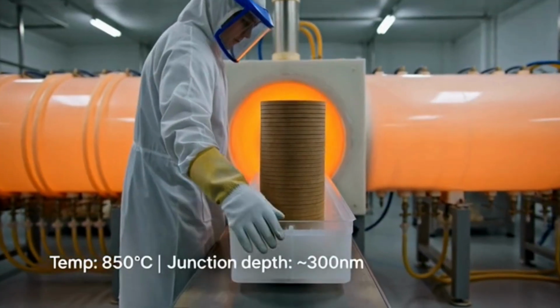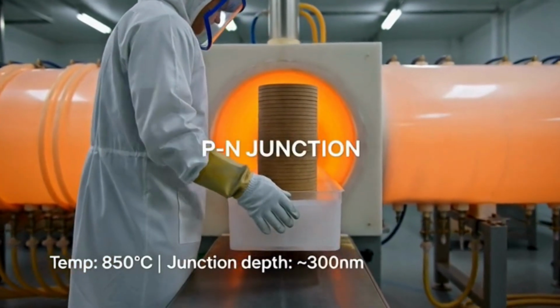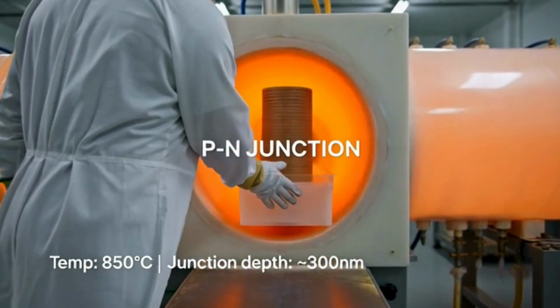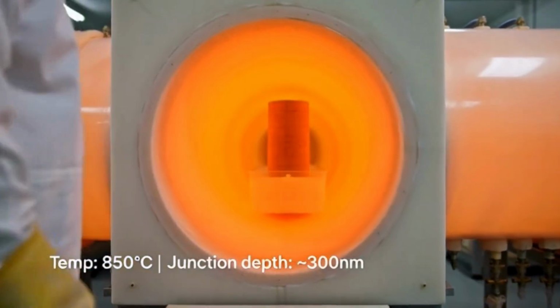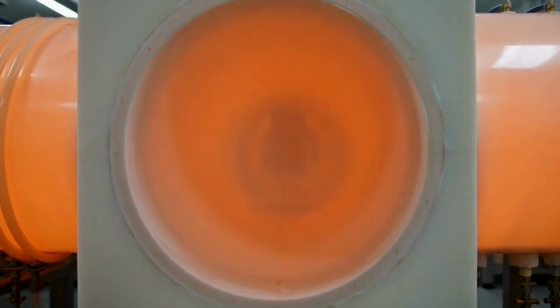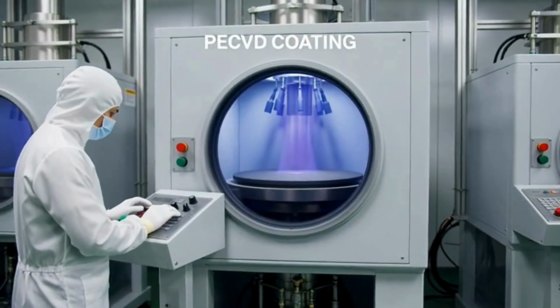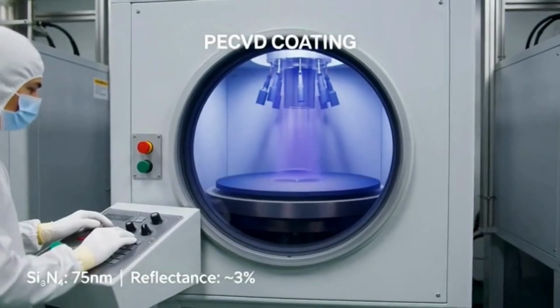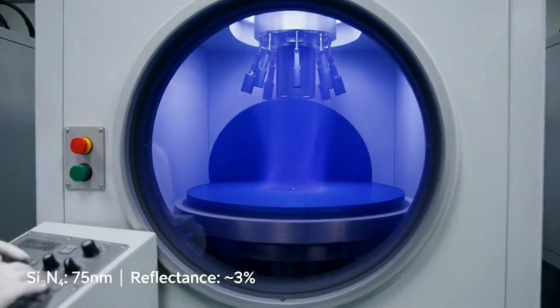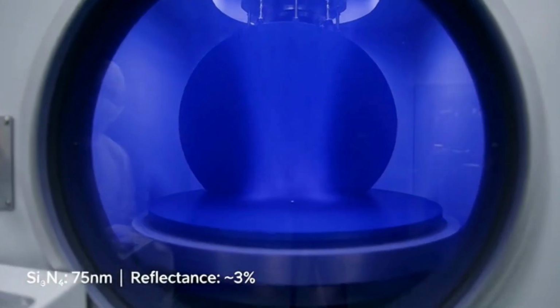At 850 degrees, phosphorus gas diffuses into the wafer's surface, just 300 nanometers deep. This creates the PN junction, the electrical heart of every solar cell. A plasma reactor deposits a silicon nitride layer just 75 nanometers thick. This anti-reflection coating gives solar cells their characteristic deep blue color.